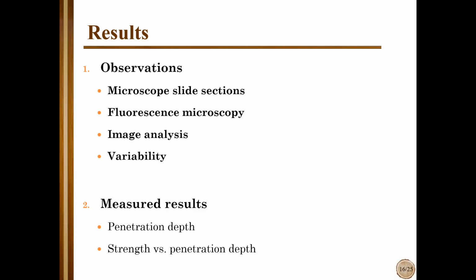The main challenge was how to prepare and stain those samples to see something under the microscope, to see high contrast between what is adhesive and what is wood. Then we used image analysis software. There is also quite a lot of variability. It depends on the person who takes measurements, how he or she decides what the threshold is for adhesive and for other material like wood tissue. And last, there is really high variability in adhesive penetration. We analyzed only a bit more than 1 millimeter of the adhesive bond line, so we repeated those measurements many times, I think 12 times, to take this high variability into consideration.